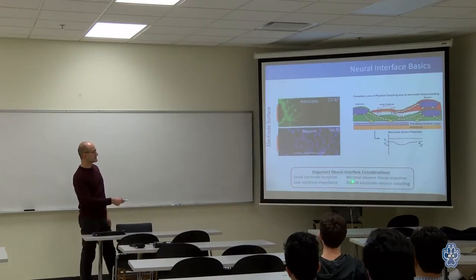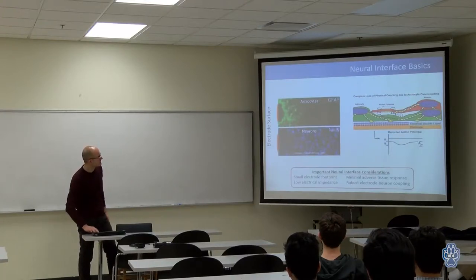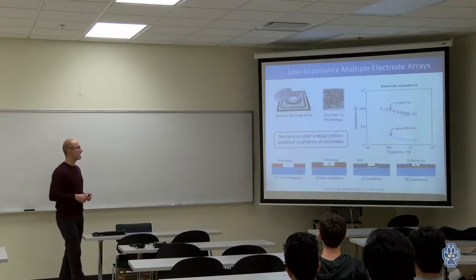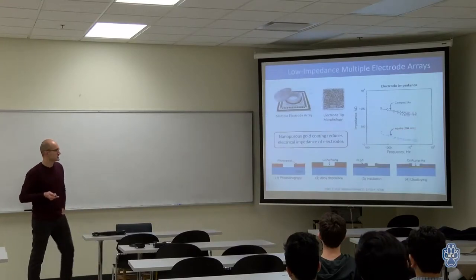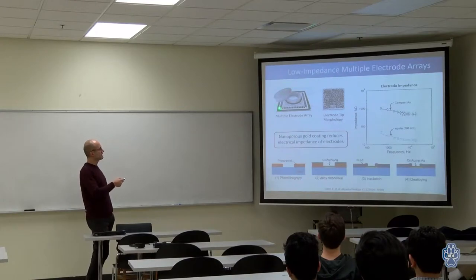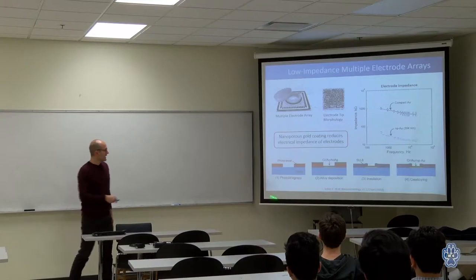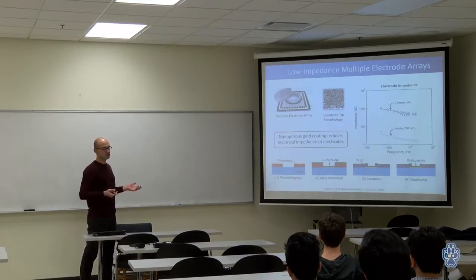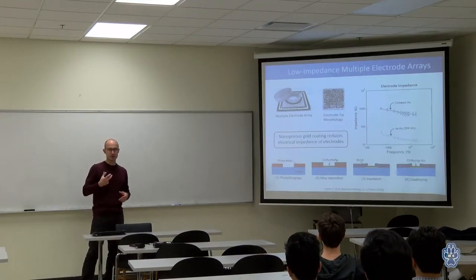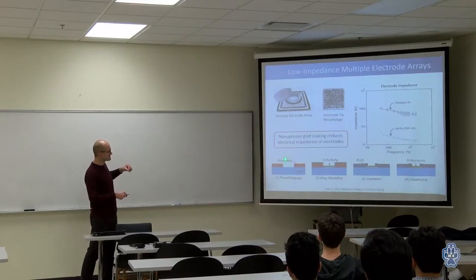Another one is you want to minimize this adverse tissue response and have the neurons attached to the surfaces as much as possible. We address the first one by using this porous electrode. What you see here is a glass cover slip, about 3 inches by 3 inches, and you cover this with a material called photoresist, a photosensitive polymer. When you expose it and develop it, the parts exposed to light come out. So now you have an opening that corresponds to these metal traces that you see.